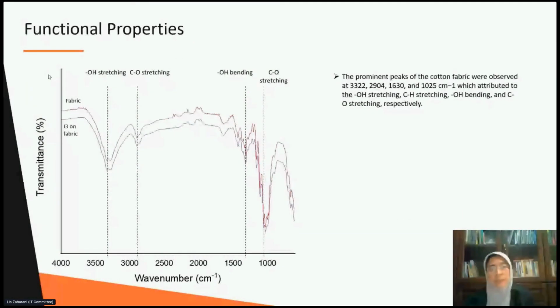The functional group results can be observed in this graph. These are the functional groups existing in the cotton fabric and the ink 3 fabric presented here. The prominent peaks of the cotton fabric were observed at 3322, 2904, 1630, and 1025 cm⁻¹, which are attributed to OH stretching, CH stretching, OH bending, and CO stretching respectively.